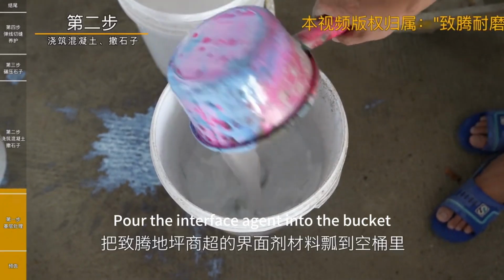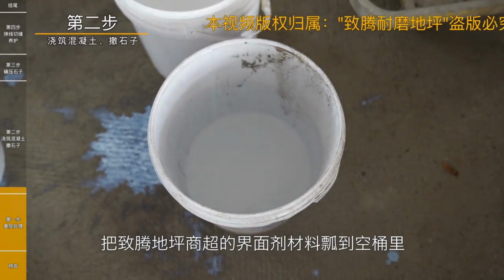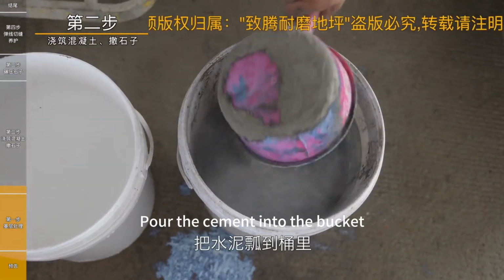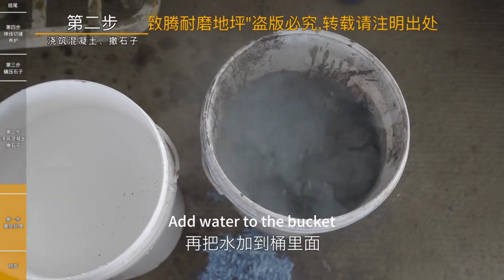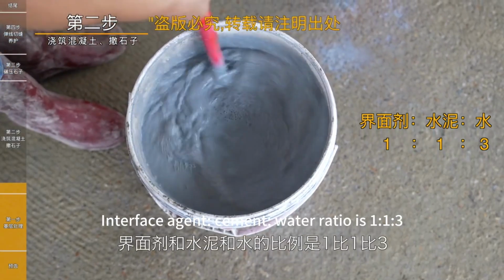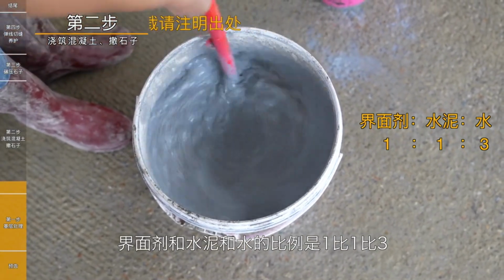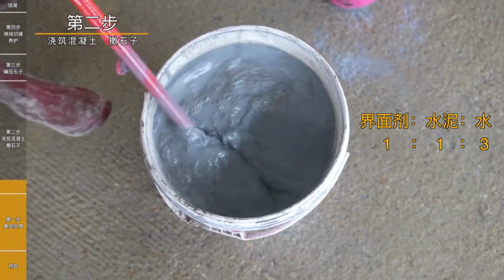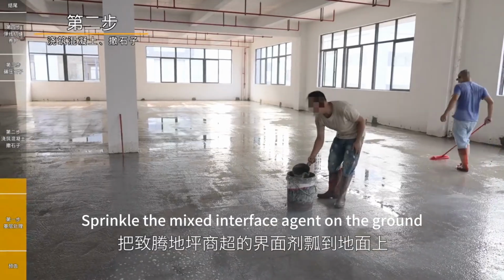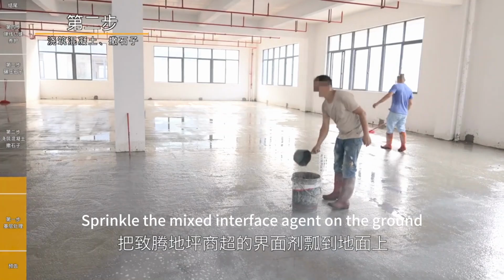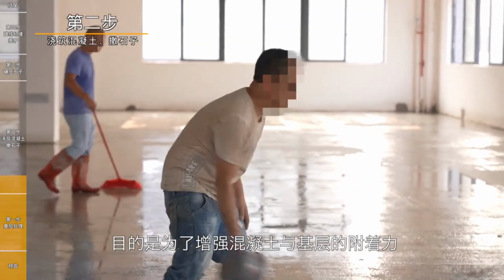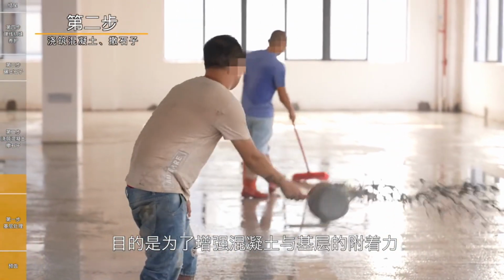Pour the interface agent into the bucket. Pour the cement into the bucket. Add water to the bucket. The interface agent, cement, water ratio is 1:1:3. Sprinkle the mixed interface agent on the ground. The purpose is to enhance the adhesion between the concrete and the base.